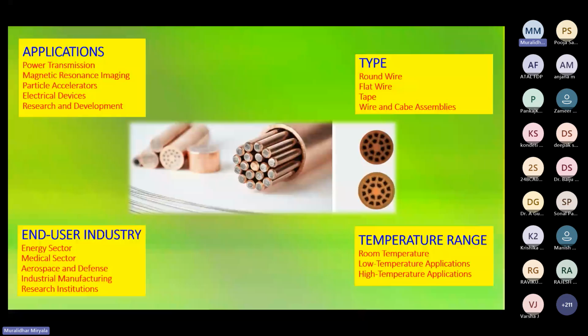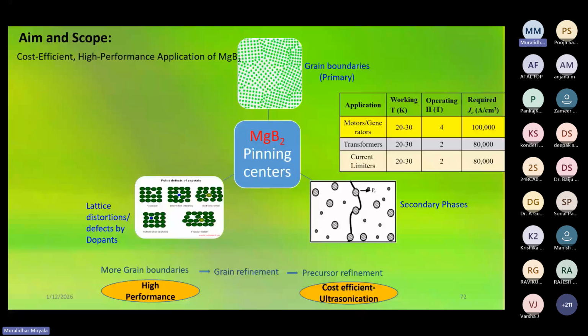Here, one of the major issues is that if you want to increase this performance, we have to increase the critical current density. What I showed in the table: motors and generators need 100 kiloamps per centimeter square, transformers 80 kiloamps, then current limiters. Here we have Mg and boron. Boron is one of the major drawbacks. Boron's melting temperature is 2200 to 2500 degrees, while magnesium is 600. Magnesium melts and reacts with the boron to form MgB2.